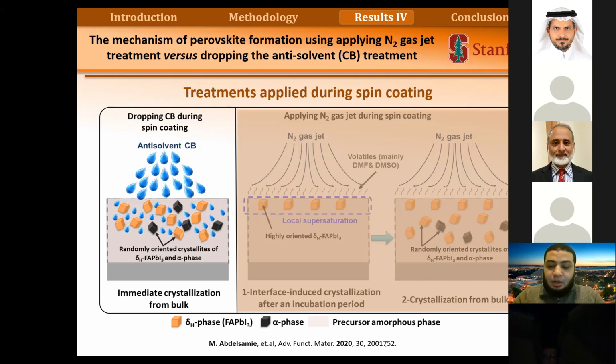They're trying to use the organics or perovskites as a supporting alternative in fields that silicon cannot apply. And in terms of efficiency, I think their limit will not reach the highest efficiency of silicon solar cells. So theoretically, some of them, if used in tandems, can reach 30% to 40%. But I think with the current status, it's difficult to even reach 30%.